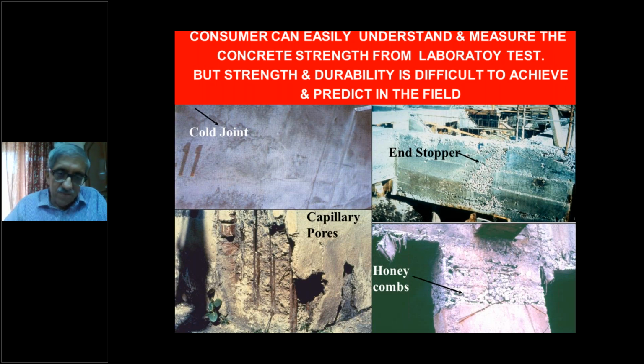We get defects, we get honeycombs, we use sometimes high water to cement ratio leading to a high amount of capillary pores, bigger capillary pores. We have reinforcement. The cubes are not reinforced. And above all, and most importantly, curing is often neglected on the site, but the cube is always cast properly, cured properly, and therefore it is likely to give a better strength than what happens actually in the field.